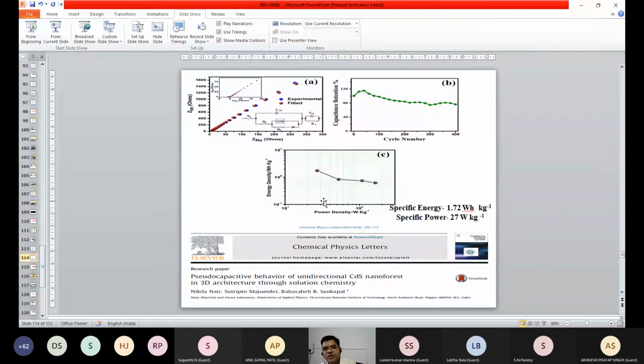Not only this, we observed that there was a stability issue with cadmium sulfide, because we converted the hydroxide part with sulfur ions, right? So it forms some detachment of the cadmium sulfide wire from the stainless steel, which is responsible for giving a lower value of stability. We checked only up to 400 cycles, and it shows a little bit lesser stability for higher cycles.